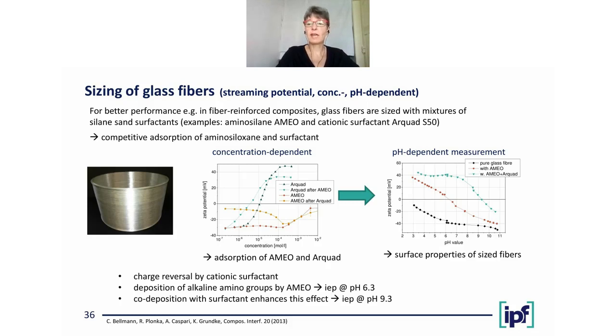Another application is the sizing of glass fibers. In our institute, glass fibers are often used as fillers or as reinforcement for polymeric composites. And to improve the filler matrix interaction, the fibers are sized. A usual method is to apply a mixture of a silane and a surfactant. In this case, the aminosilane and the cationic surfactant. To do this in an economic way, it is important to study how this adsorption takes place, especially if you have a competitive adsorption of the two species.